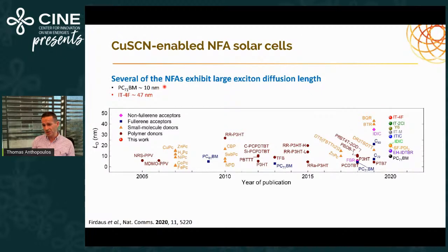This is not surprising because similar numbers have been reported many times in the literature. But what was very intriguing to us was that a lot of the NFAs exhibited quite a high, long exciton diffusion length. IT4F, for example, reached up to 47 nanometers, which was perhaps one of the reasons why these NFAs are also very good at producing high performance OPVs.